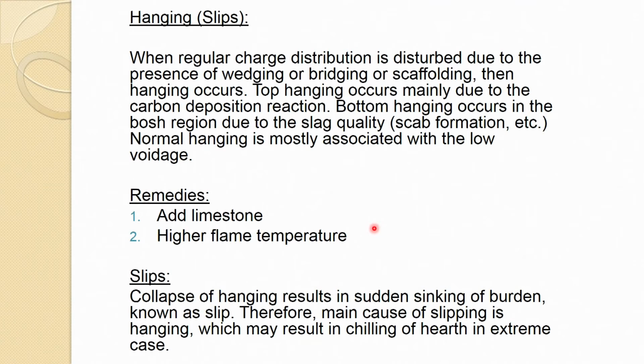Another abnormality is hanging, that is, hanging and slips. These are two things I said, but we will discuss them together because they are related. So, when a regular charge distribution is disturbed due to the presence of wedging, bridging or scaffolding, then hanging occurs. Top hanging occurs mainly due to the carbon deposition reaction. We discussed the solution loss reaction where the carbon deposition occurs, and when this occurs, it hinders the descent of the charge, and this may occur in the top section. Bottom hanging occurs in the bosh region due to the slag quality, scab formation, etc. Normal hanging can occur anywhere where you have a low voidage.